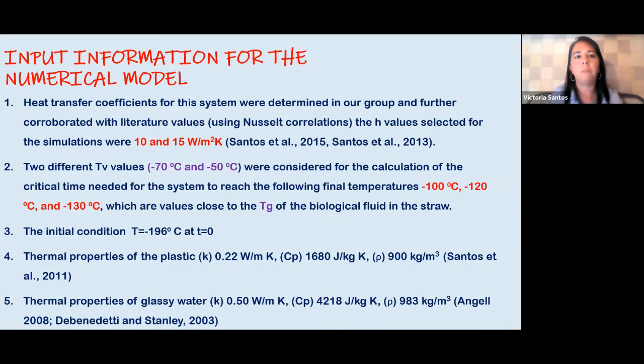So what do we need in the numerical model? We need the heat transfer coefficients that we have determined in our group, and we also corroborated these values with literature values using the Nusselt correlations. And we selected and calculated they were between 10 and 15 watt over square meter degree Kelvin. We selected two different nitrogen vapor temperatures, -70 and -50 degrees, and they were considered for the calculation of the critical time needed for the system to reach a final temperature that would be -100, -120, or -130. These are values close to the TG of the biological fluid.